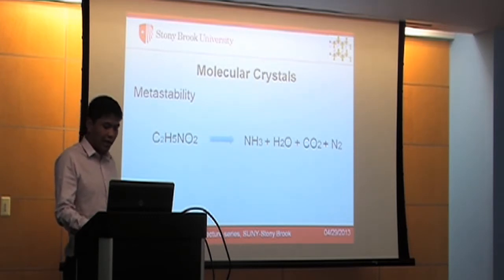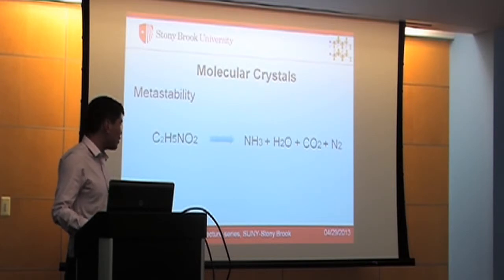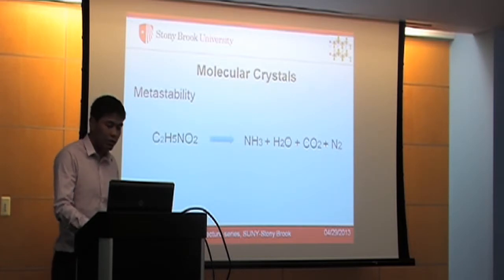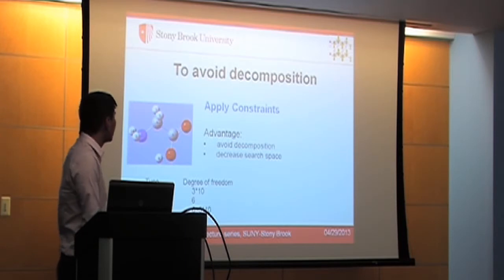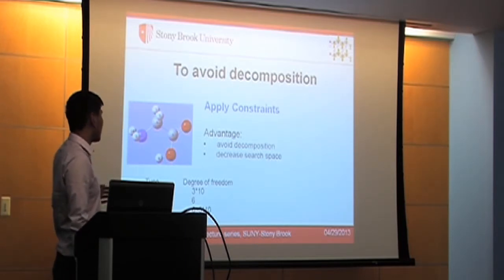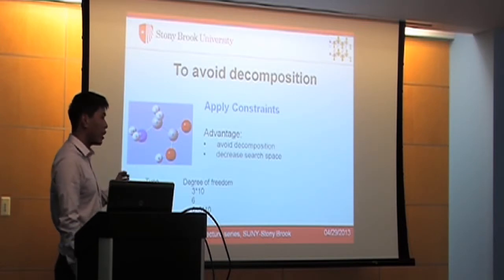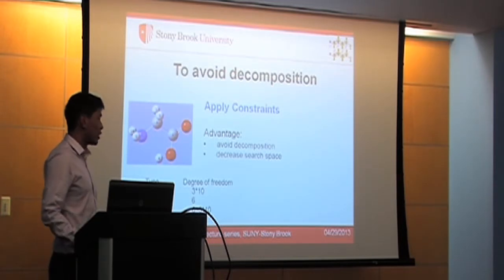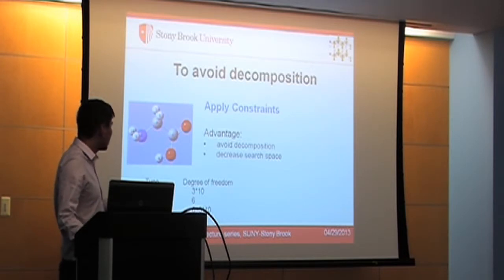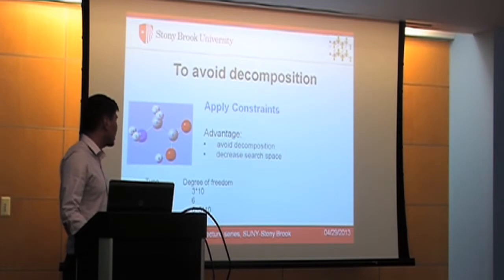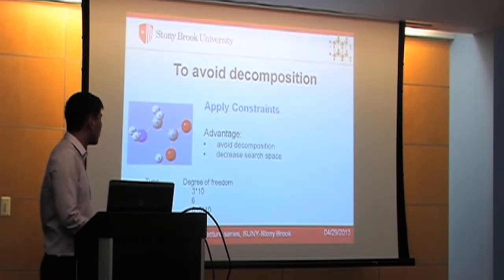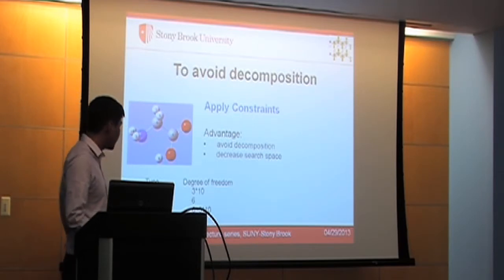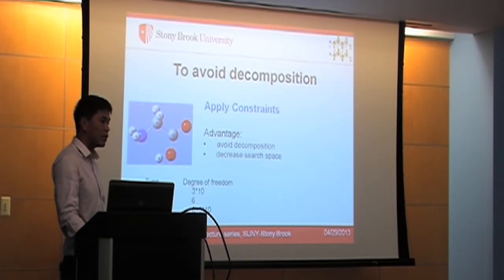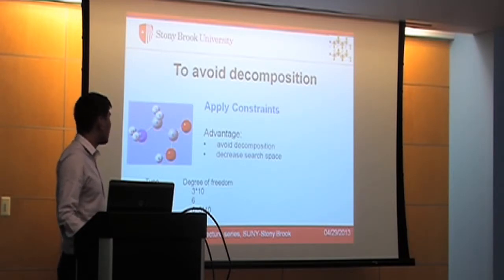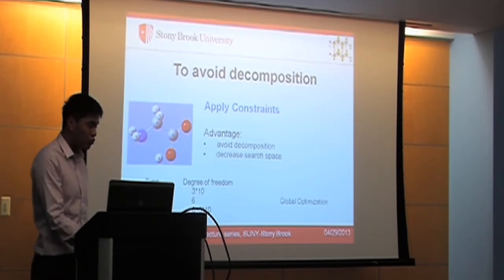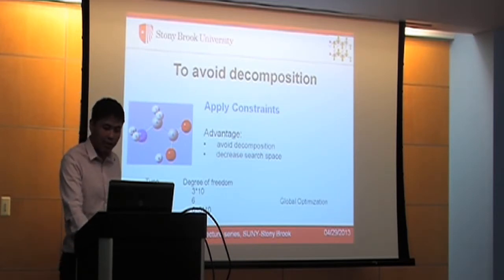So it proposed an issue that we need to avoid such kind of decomposition of the molecules when we perform our search. So the most straightforward way is to apply constraints. So we can treat it as a whole building block. So during any operations, we always keep the geometry of this building block. We constrain it as a rigid body, so the benefit from this is not only that it can prevent the decomposition, but it can also decrease the number of degrees of freedom for each molecule, which can further decrease the searching space quite a lot, which is exponentially related to the number of degrees of freedom. So in this case, we are no longer doing global optimization, but constrained global optimization.